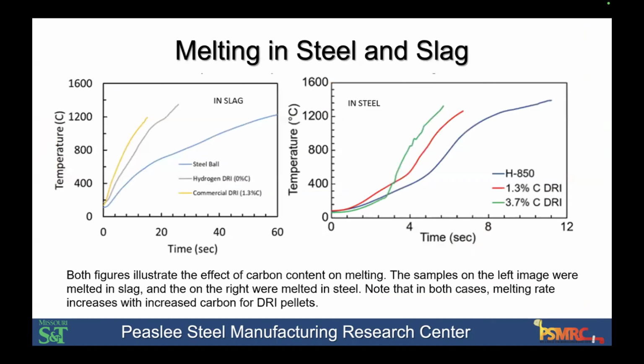steel or slag. If you look at these traces of measurements, you can see the heating rates go up as the carbon content of the pellet goes up. And this is because of that gas evolution reaction. Now, the reaction itself is endothermic. But it's very clear that the endothermics are well overcome by the enhancements in the heat transfer by the gas evolution reactions. Here you can see the 3.5% carbon or 3.7 carbon heating and melting rates are a lot faster than the 1.3 and faster than the hydrogen pellet, which has 0 carbon in it.